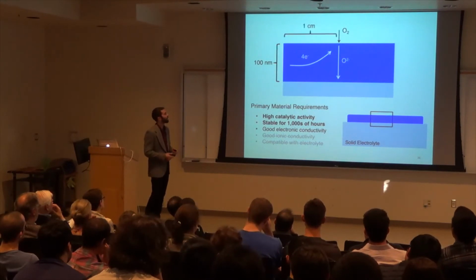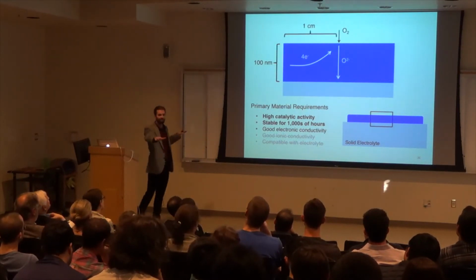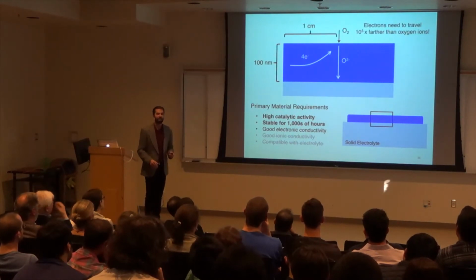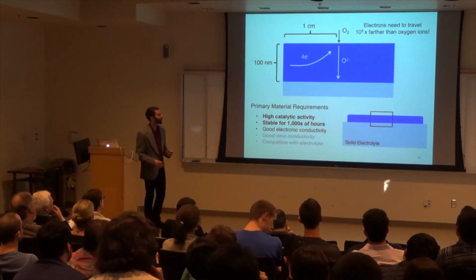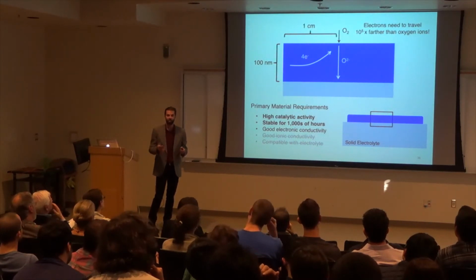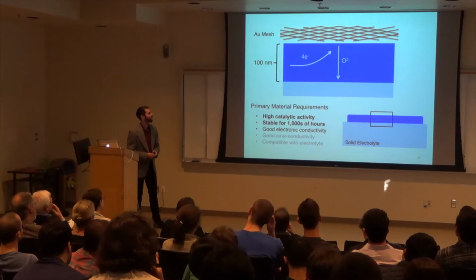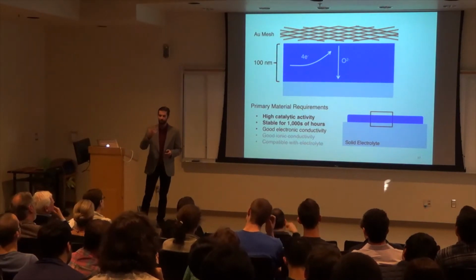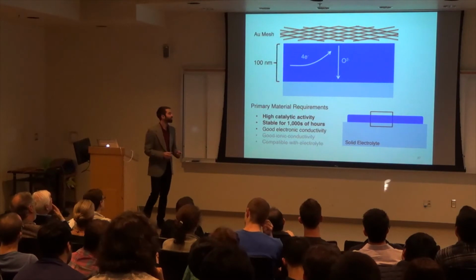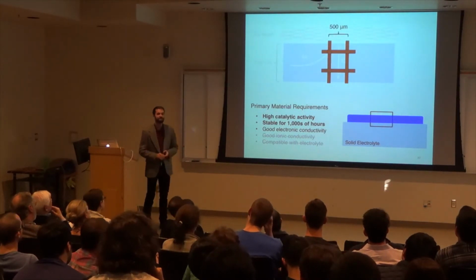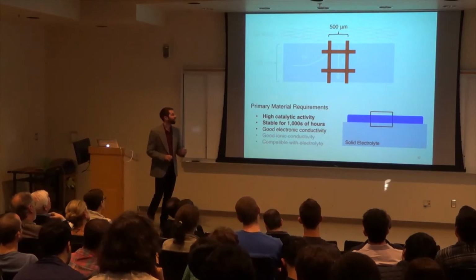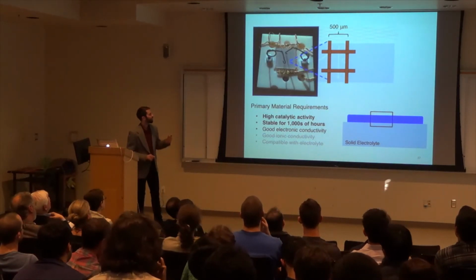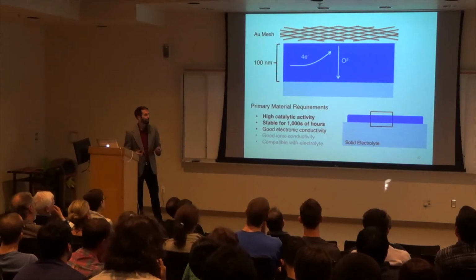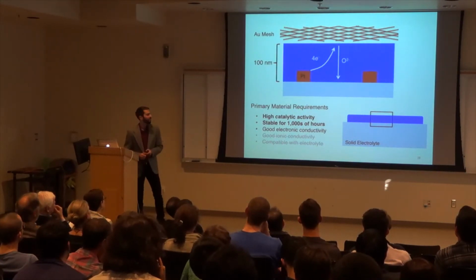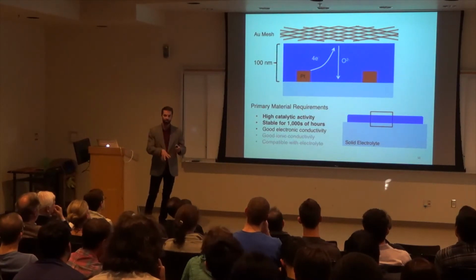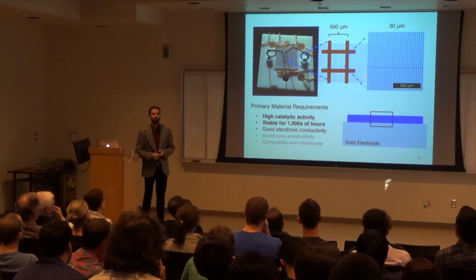But what you do have to worry about is that the aspect ratio for the distance that the electrons have to travel is 10,000 or 100,000 times farther than that of the ions. So we need to essentially engineer a way to rule that out. The first thing that we did was put gold mesh on top. Gold mesh in bulk gold is considered to be inactive as a catalyst. And so if we do that, we can decrease the distance that the electrons have to travel to 500 microns. And this is what it looks like in reality. But that's not good enough, based on our simulations. What we do to overcome this further is we bury platinum current collectors underneath the film. And when we do this, now the electrons only have to travel 30 microns.